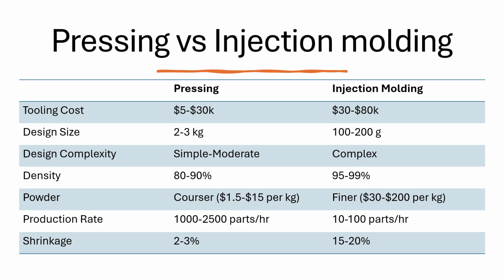The initial tooling cost for injection molding is significantly higher at $30,000 to $80,000 versus for the pressing, which is only $5,000 to $30,000. The design size for injection molding is also significantly smaller at only 100 to 200 grams versus the conventional press's 2 to 3 kilograms. Injection molding also has significantly more complex designs that it's able to create versus the pressing, which has very simple to slightly sophisticated designs. Injection molding is also capable of creating 95 to 99% dense material versus the conventional pressing that can only get to 80 to 90% after sintering. This creates better material properties, especially in tension.